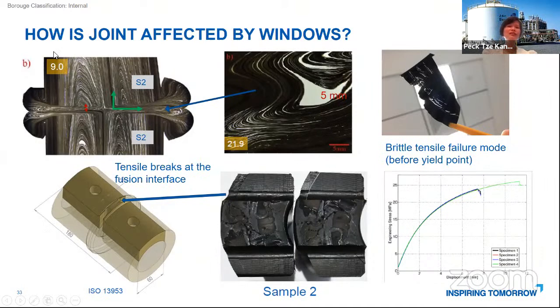So what happened when we joined those pipes with very poor dispersion? We cut the same way across the joint and did a microscopic analysis. We can see that there is not very good fusion between the two pipe ends. The different matrices of the white area and the black area are actually interfering with the mingling of the melt front.